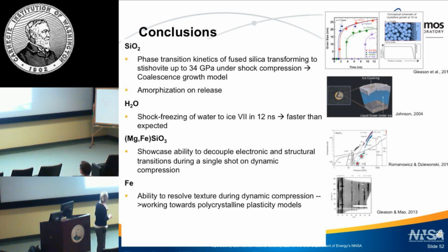So that's really interesting. The iron-bearing perovskite shows, we think, mutual structural and electronic transition. Deciphering the onset of those two transitions is still to be determined, but the opportunity is there. And then finally with iron, we are poised at the point to look at the strength of iron on the Hugoniot and follow texture evolution, and maybe add some more insight into how the anisotropy in our innermost inner core was established.